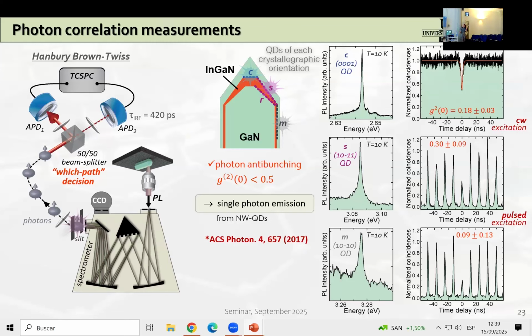And this basically shows that we are indeed dealing with anti-bunched light emission. The reason why this coincidence rate in all three cases is not going completely down to zero is because we have some background photons, which are also collected by the system, and also because the system has a limited temporal resolution. So if we correct these measurements for both background photons and limited time resolution of our measurement